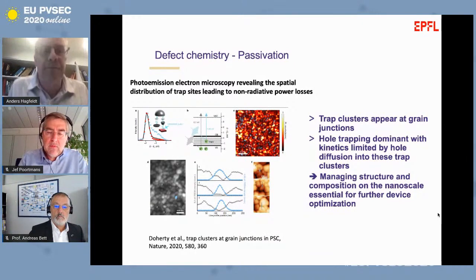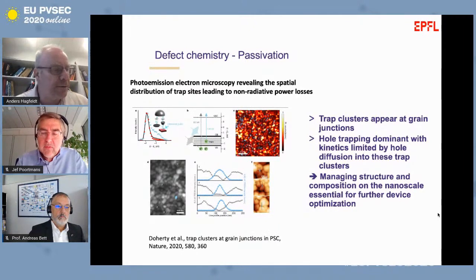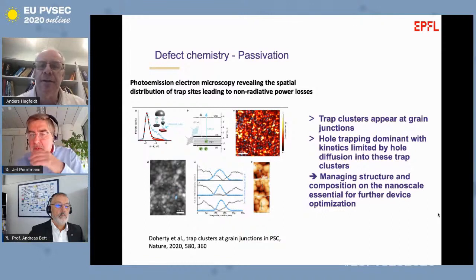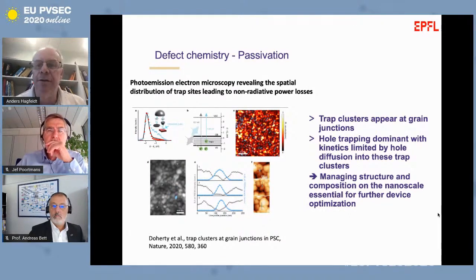coherent photoluminescence, and they use confocal photo and photoemission electron microscopies to study where we have the traps where we have non-radiative recombination. That's what we want to avoid. And in this work in Nature, they conclude that it's not a homogeneous trap distribution. It clusters at grain junctions and grain boundaries.